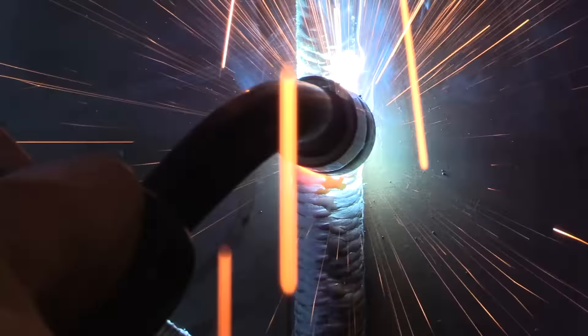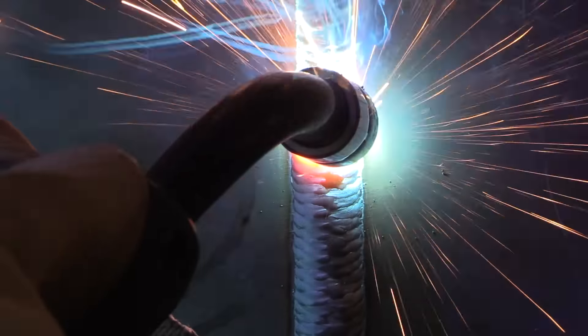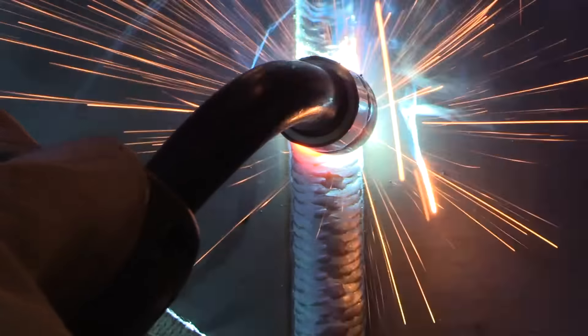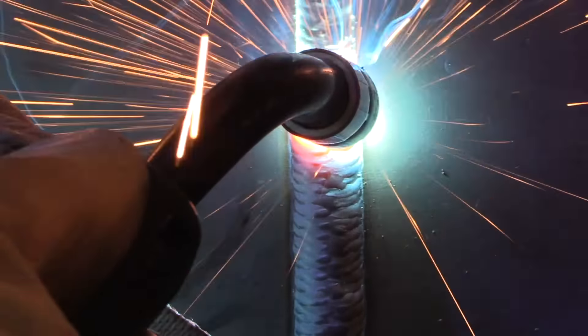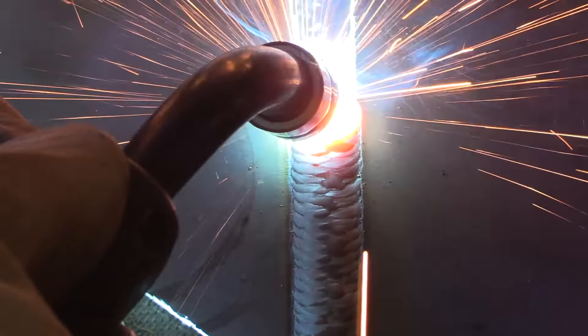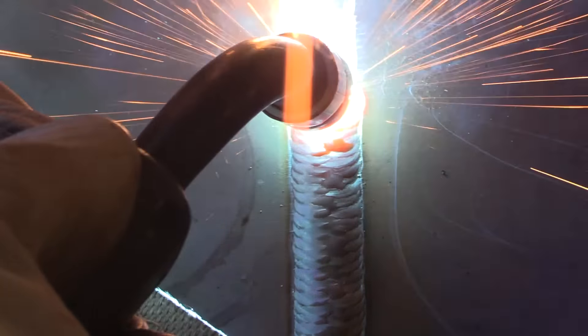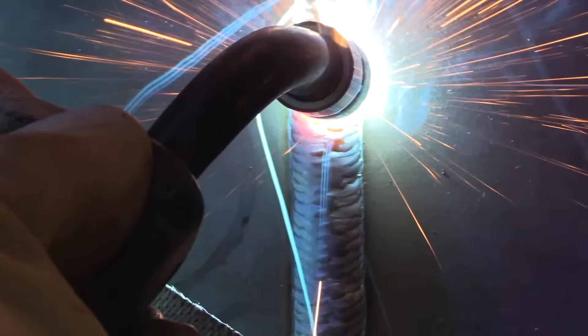Again, holding the toes just briefly and not spending a whole lot of time across the middle. I'm not bouncing from side to side. I'm just not going really slow. And then I'm trying to overlap those edges of the bevel just by about a sixteenth of an inch and trying to do it the same each time.